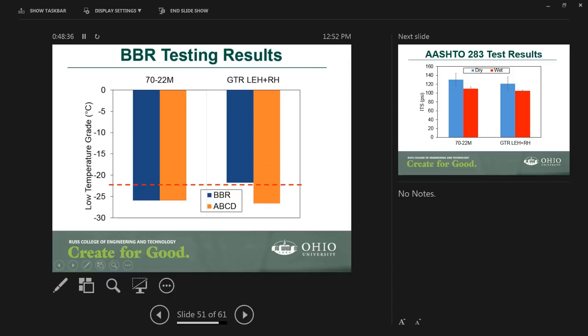Again, I think that BBR has some issues when it comes to highly modified binder. But in all cases, the results for the GTR in terms of the BBR were lower, or warmer, I would say, than the minus 22. In terms of the ABCD, it actually was higher, or better.